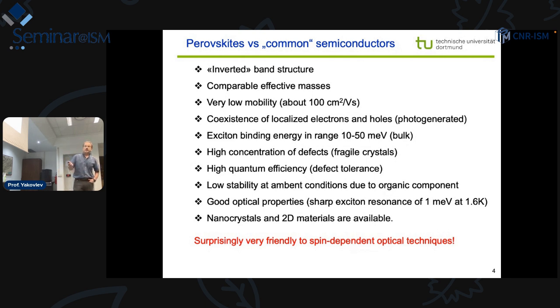Good optical properties, surprisingly. At low temperatures, the exciton resonance can be only 1 millielectron volt. So one can, if we make single crystals, I'm talking not about polycrystalline films, do nice spectroscopy on these semiconductors, and also nanocrystals and two-dimensional materials are available.